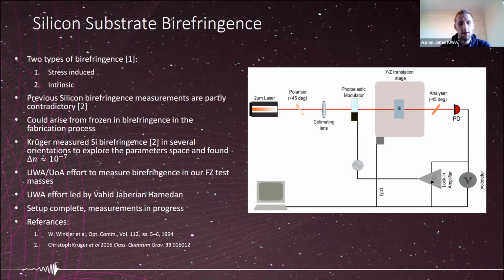We've got a bit of an OzGrav-wide effort to characterize this. And again, this is led by Vahid. I've got a sketch of his setup on the right-hand side. We've got some polarization modulation, and we're passing it through the silicon sample. We're going to measure the birefringence at several different spots over this test mass. This optical setup is complete, and Vahid's working diligently in the lab to obtain some results there. And again, this is just for our test masses.